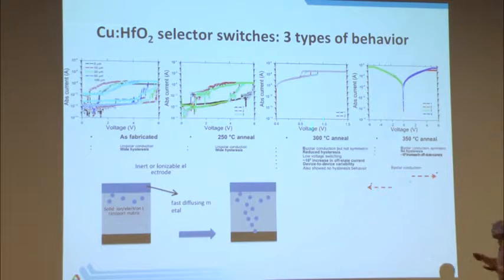If you anneal them, then you change the microstructure and you allow them to then turn on at much lower voltages. The data is a lot cleaner, as you can see. The current changes as a function of voltage. And then when you anneal them further, this is an oxide, but it behaves almost like a semiconductor with a much lower band gap, which is also very interesting. And we are doing some electron microscopy work to try to figure this out.